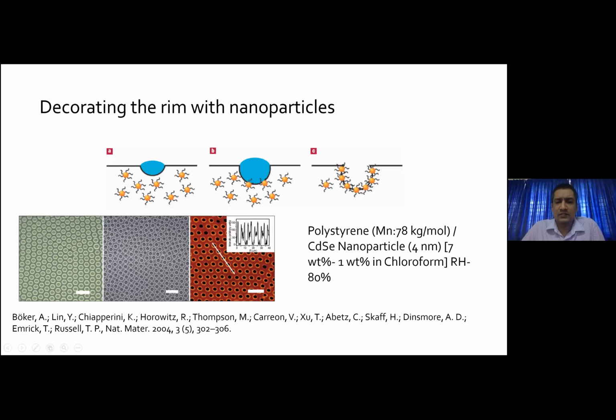Another approach to decorate the core is to see whether I can put nanoparticles, like what is shown here, where you take, sorry, not gold nanoparticles, cadmium selenide nanoparticles, which are of a dimension of a few nanometers. If you recollect, this dimension is, let's say, a few microns, and this is a few nanometers. Then you try to decorate this inside lining by allowing the cadmium selenide nanoparticles to migrate from the bulk to the periphery by modulating the solvent conditions.